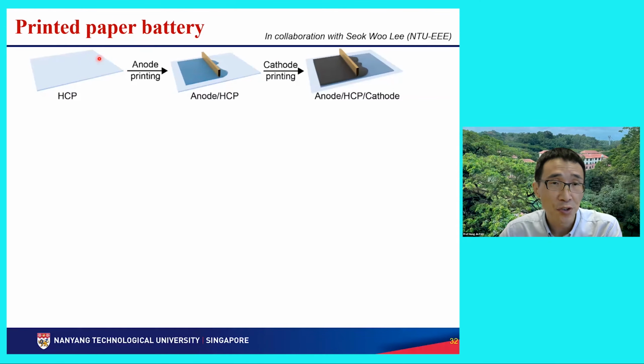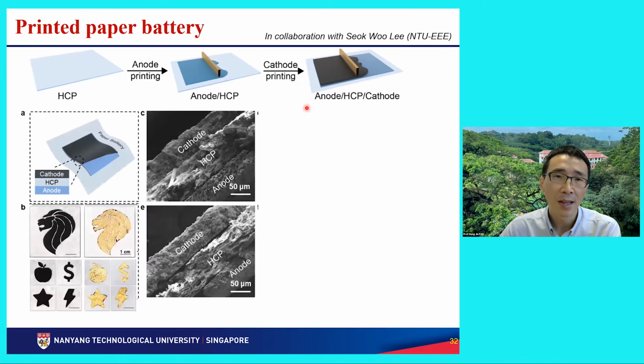On this kind of engineered paper, on the top side and bottom side, we can use doctor blade printing of anode and cathode materials. This one is in collaboration with my friend Seok Woo Lee in NTU-EEE. So this is the battery structure, and this is a scanning electron microscope image of the cross section of the battery structure. This is the cathode material, which can be manganese or nickel, and this is the anode, which can be zinc. You just make the ink and print on the top and bottom surface of the hydrogel paper.